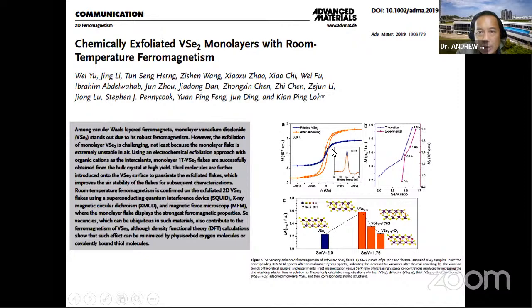And the interesting thing is that when you have pristine material, the magnetism seems very small. But after annealing, you can see a larger hysteresis here. And when they did computations, they found that if the vanadium selenide was intrinsic before annealing, the magnetism is lower. But when you anneal it and it becomes selenium deficient, so VSe1.75 here, it becomes more magnetic, consistent with this experiment. And if you saturate the vacant selenium vacancies with thiols or oxygen, the magnetism drops. So this suggests that the defects seem to play a role in the magnetism.